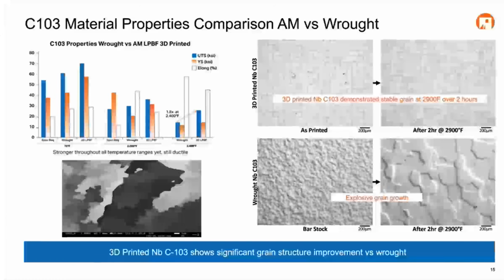The grains are too refined to really clearly pick out at this magnification, versus we can kind of see individual grains here in this view. And then if we expose this material at 2,900 degrees, almost 3,000 degrees Fahrenheit, for 2 hours, we can see the difference this has on the different types of material.